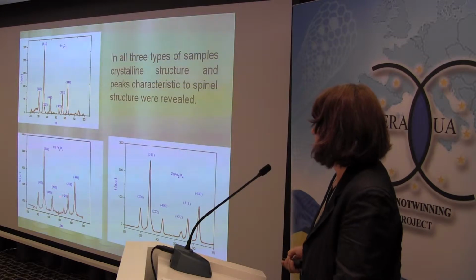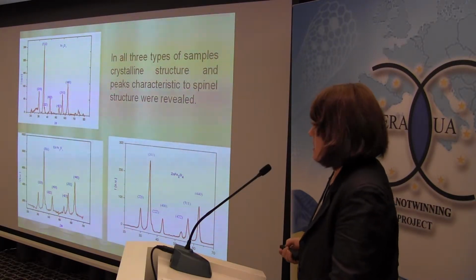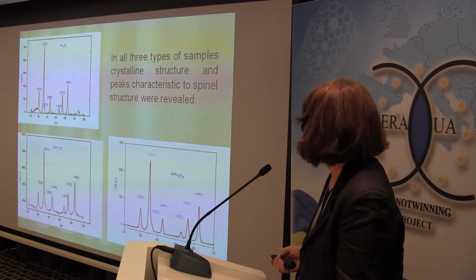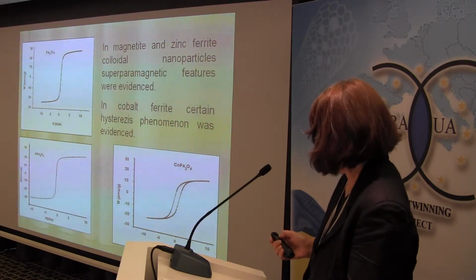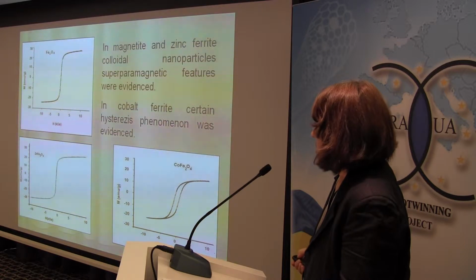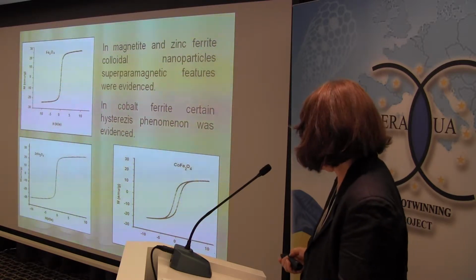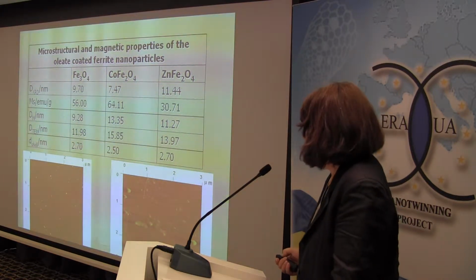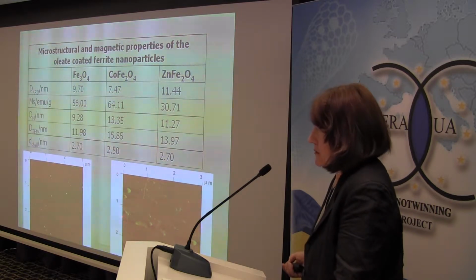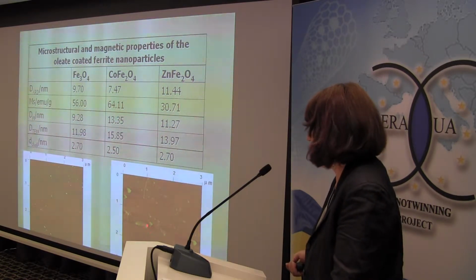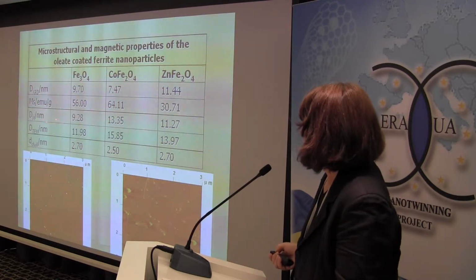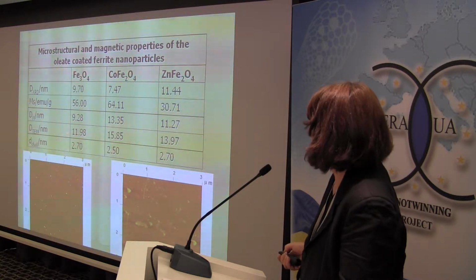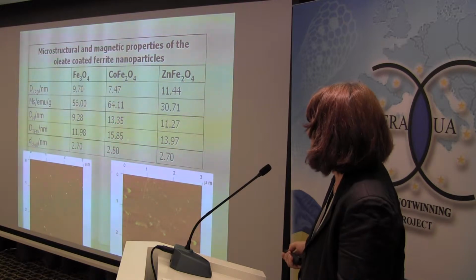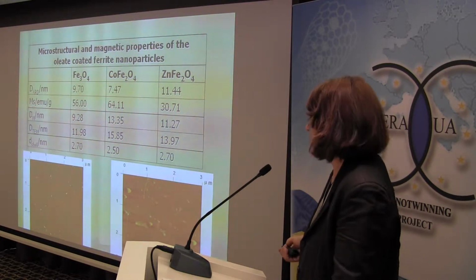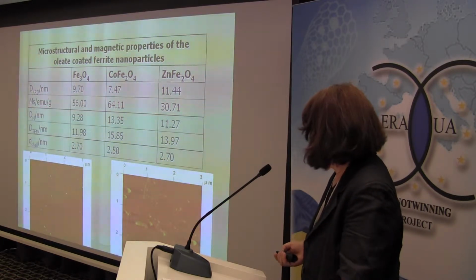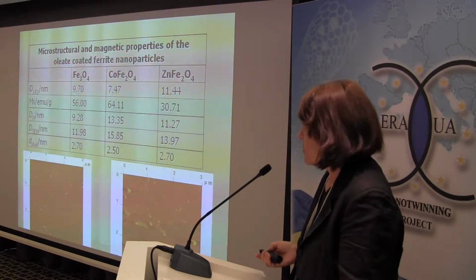Here are the results for the X-ray diffractometry. In all cases, a typical structure of spinel, and no other supplementary peaks, no peak missing. Here are the magnetization data with no hysteresis, meaning superparamagnetic behavior, except this cobalt ferrite, and this was because of higher particles and earlier agglomeration that we found by atomic force microscopy. Even from the other methods of diameter estimation, magnetic or transmission electron microscopy, it was shown that particles are higher than for the other particles. So we have to work more on this method regarding the details for optimization.